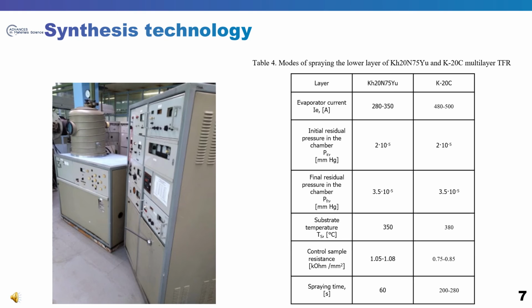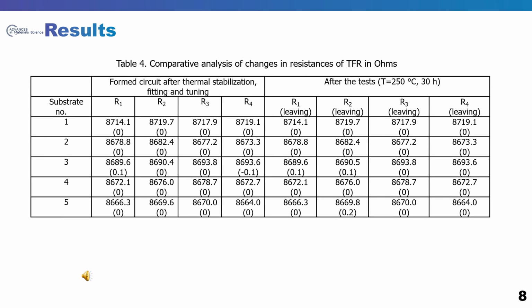The modes of thermal stabilization of the formed thin film from alloy are performed in two stages: thermal cycling in vacuum, and heat treatment in air. In order to develop the necessary stabilization modes and achieve the specified temperature-time stability, additional temperature tests of the thin film from alloy were carried out in air at a temperature of 250 °C. The results of the film resistance measurements during the tests are listed in the table on the slide. According to the results of temperature tests in air, it can be seen that the change in the resistance of the thin film from alloy is insignificant. Therefore, it was decided to stabilize the obtained multilayer thin film by a combined technology in vacuum and air.